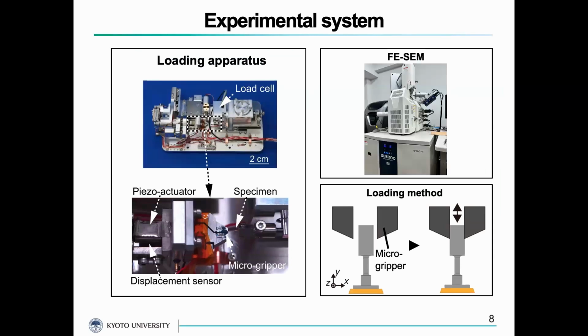The experimental system was composed of our developed loading apparatus, a field emission SEM, and a controller. The developed loading apparatus was composed of a load cell, a piezoelectric actuator, a displacement sensor, a micro gripper, and a stage. Tension and compression loading was applied to the specimen by gripping the head of the specimen using the micro gripper.